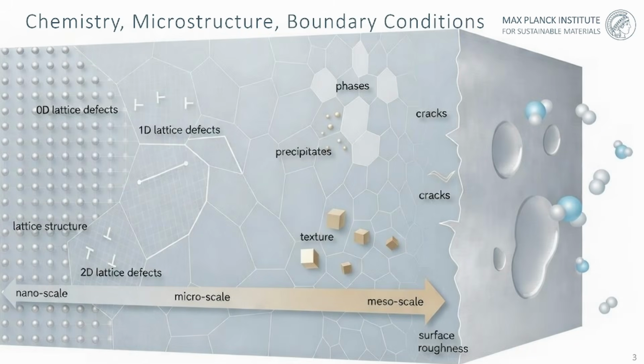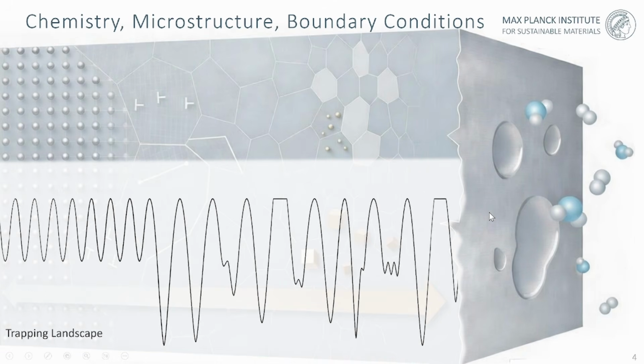Another very important aspect that makes research on hydrogen embrittlement so complicated is when you look at a schematic of the cosmos of microstructure and defects in complex metallic alloys, from the lattice defects to grain boundaries, to texture, to phases, to surfaces, and so on. You must understand that it is also the loading condition of hydrogen that makes this problem really challenging. When you consider a trapping landscape for hydrogen in such complex microstructure scenarios, then you can understand that the trapping landscape is very different, and trapping depths for hydrogen can be very diverse depending on the nature of the defect that is being affected by intruding hydrogen.